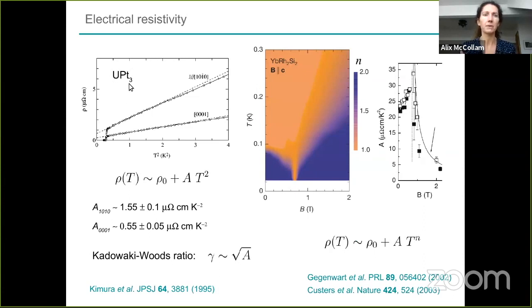So again, I'm using uranium platinum 3 because it is a good Fermi liquid and it's nice to see. This is the resistivity as a function of temperature, with this rho naught plus a T squared Fermi liquid-like behavior of the A coefficient when you have a Fermi liquid. In this case, uranium platinum 3 is a good Fermi liquid, and you can see this plot against T squared gives you a very nice linear relationship with an A coefficient of, this is 1.55 along the AB direction and 0.55 along the C direction. The relationship to the renormalized specific heat comes through the Kadowaki-Woods ratio in that case. It's not always held, but it's very commonly observed, this ratio in the heavy fermion materials.